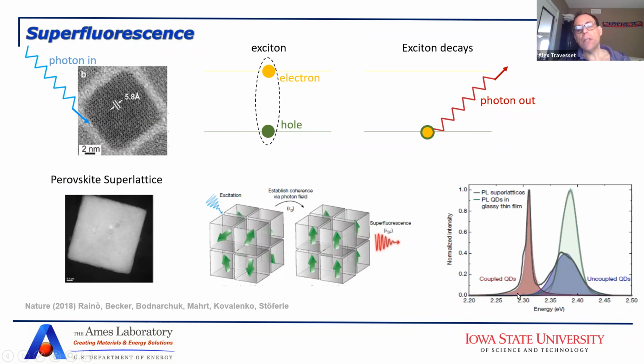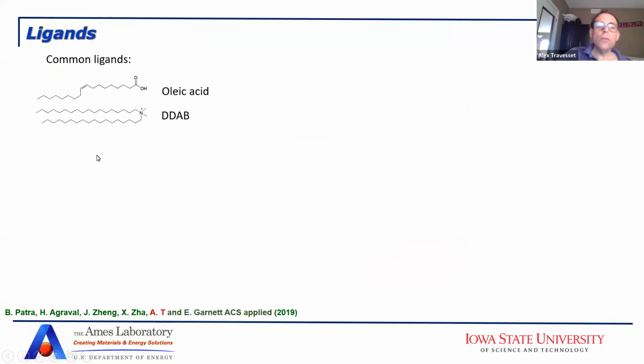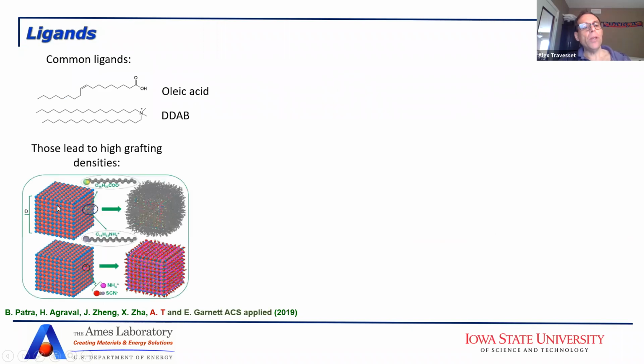What is important here is that this only happens when you put these nanocrystals in a simple cubic lattice. It doesn't happen when they are in some amorphous type material. So we looked at what happens with these perovskites and how to assemble them. Here we have an example of our early work. Those are typical superlattices. There are different types of ligands that you can put. And this is what it looks like.